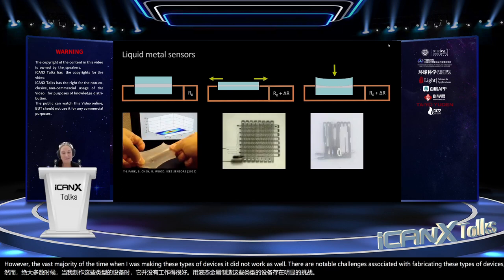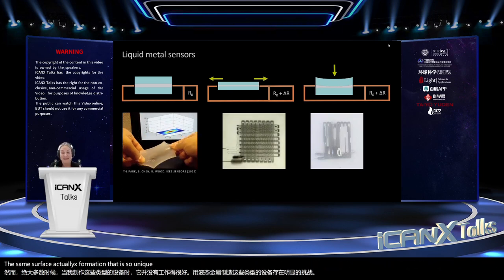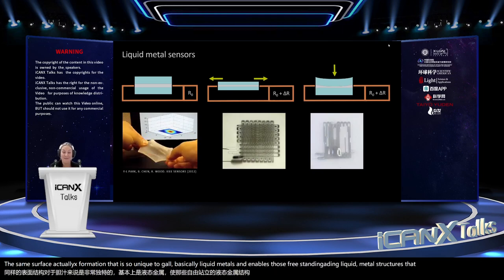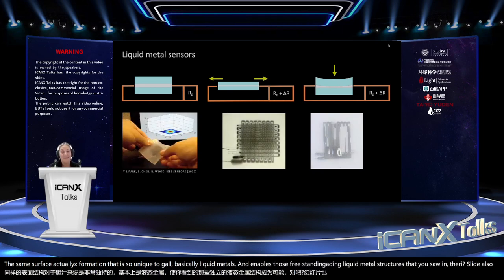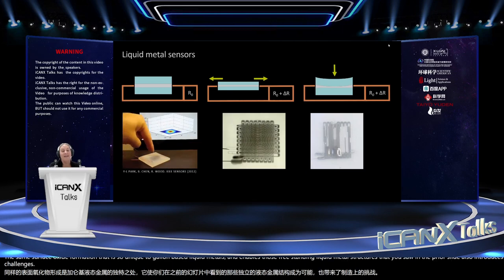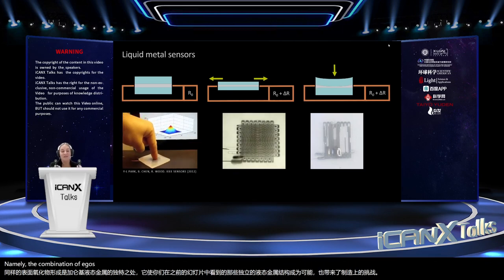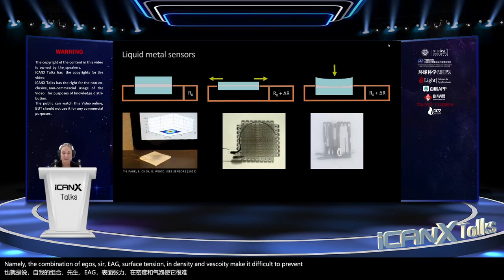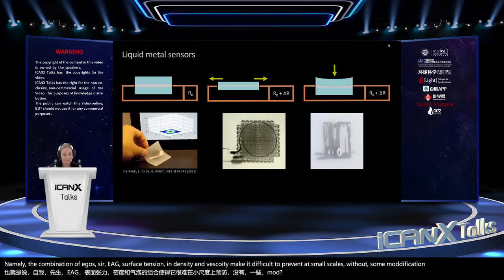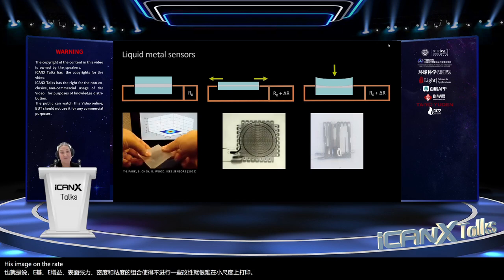The same surface oxide formation that is so unique to gallium-based liquid metals and enables those freestanding liquid metal structures that you saw in the prior slide also introduces these fabrication challenges. Namely, the combination of EGaIn's surface tension, density, and viscosity make it difficult to print at small scales without some modification. So this image on the right shows a failed fabrication attempt.